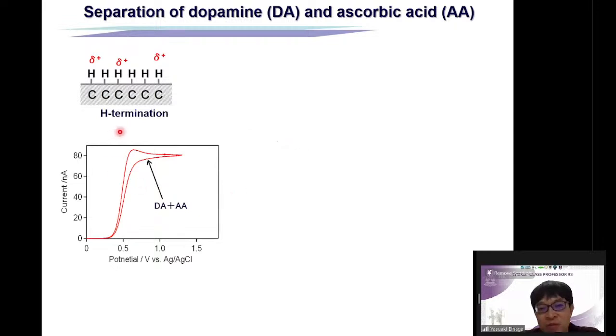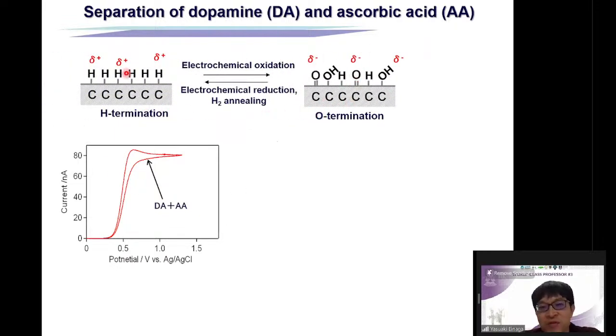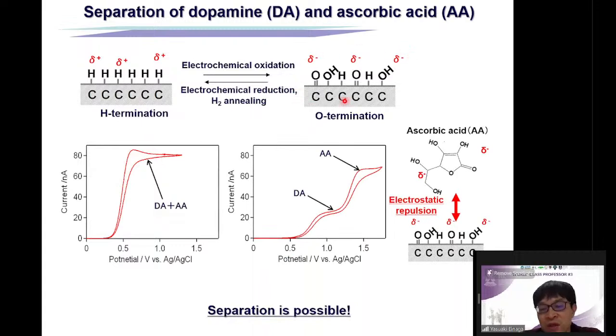But by using boron-doped diamond, we can control the surface. As I mentioned before, the hydrogen termination can be converted to oxygen termination. With hydrogen termination, dopamine and ascorbic acid show the same potential. However, with oxygen termination, the peaks are different: dopamine and ascorbic acid show different oxidation peaks. Why? Because ascorbic acid is negatively charged and the oxygen termination is also negatively charged. This electrostatic repulsion can shift the oxidation potential of ascorbic acid, so we can separate these two peaks and detect dopamine in the brain.